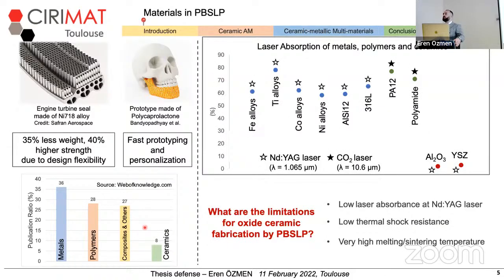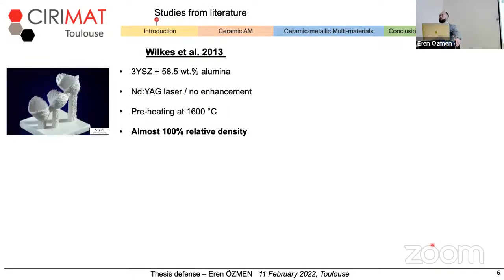So what makes them, especially white oxide ceramics such as alumina or zirconia, limited for this process? The first limitation is their low energy absorption, especially under Nd:YAG laser wavelength. Another limitation is their low thermal shock resistance, which is a problem in a process where very high temperature, very high energy is transferred to the material in a short time. And also their very high melting and sintering temperature, which is quite challenging to reach in a limited time as well. To overcome these three issues, various strategies were applied in literature.